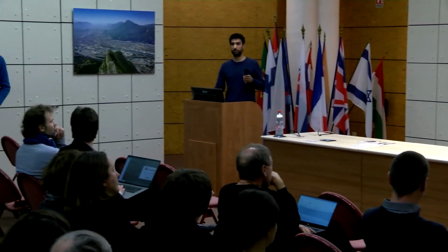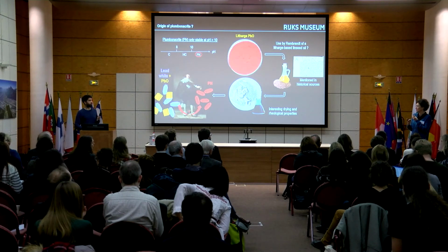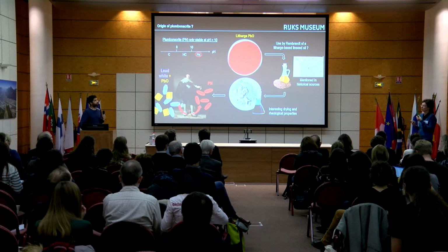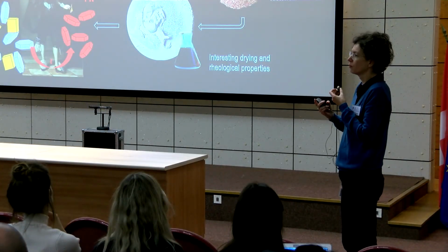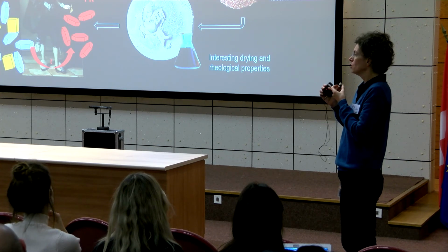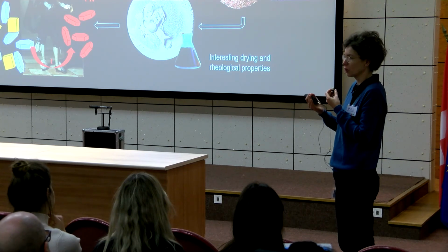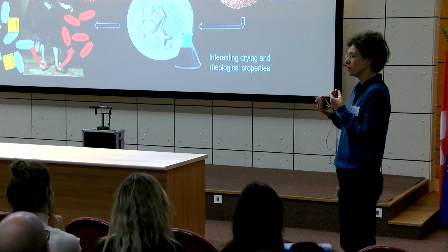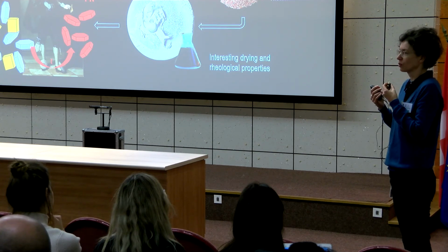Some other questions? Or it may be that in the samples where you detected plumbonacrite, it also comes from lead oxide. Yeah. But basically, our hypothesis is that when we found plumbonacrite, it means that lead oxide was probably used, and probably at such an extent or with particles so big that it remained available for reaction with CO2 and water to form plumbonacrite, even if there are probably many cases where litharge was used but completely reacted with oil to form lead soaps.